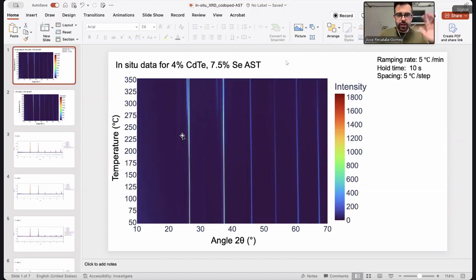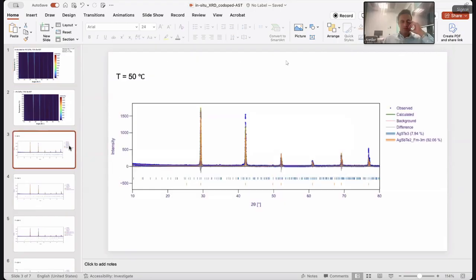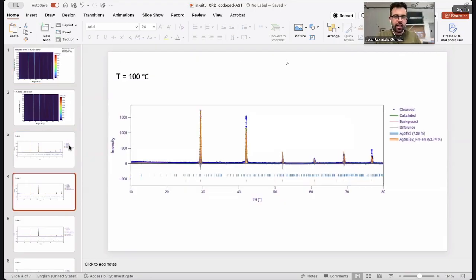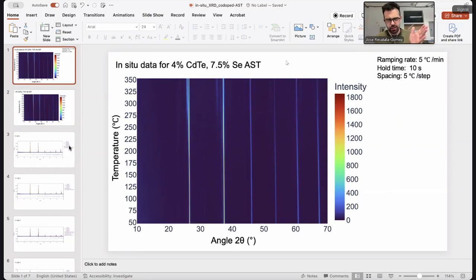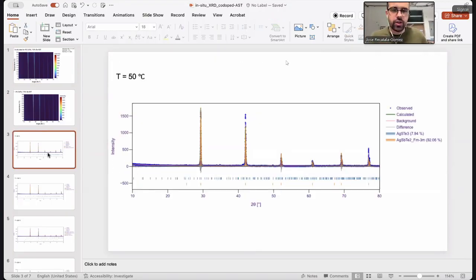And as temperature increases, you notice that this peak appears, and these little peaks also appear, right? And it's quite nice because you can correlate that. I have data every 5 degrees; the granularity of this data is 5 degrees per step. The ramping rate was 5 degrees per minute, and I held for 10 seconds per scan. And for those of you that might be concerned that I'm not scanning for a long enough time, just a quick reminder that for you to be able to do Rietveld refinement on a material, your most intense peak should have a factor of 1,000 counts over your background.